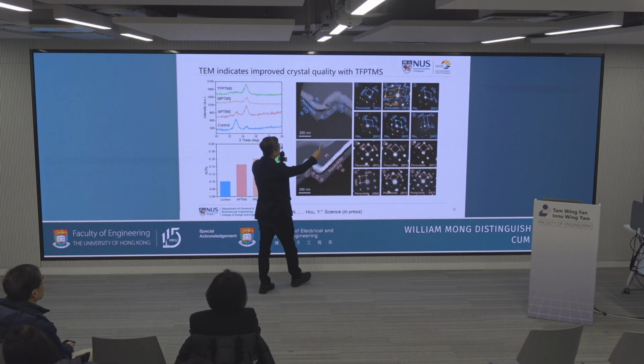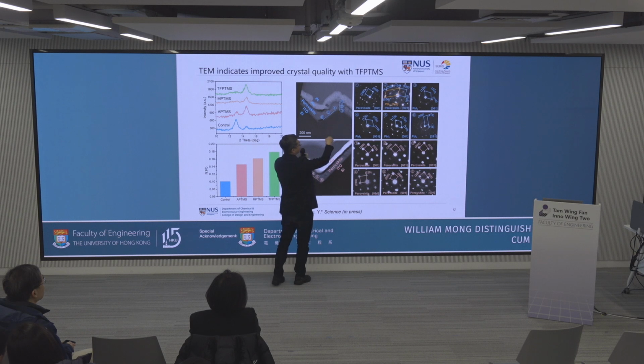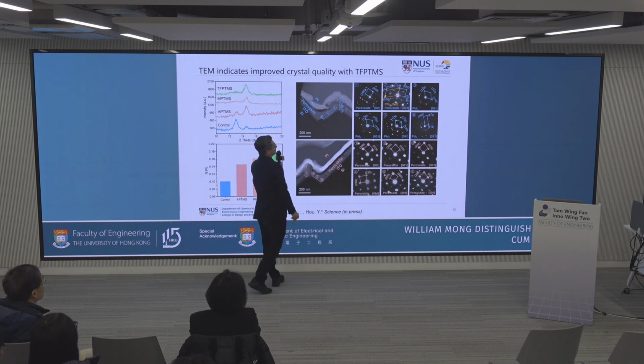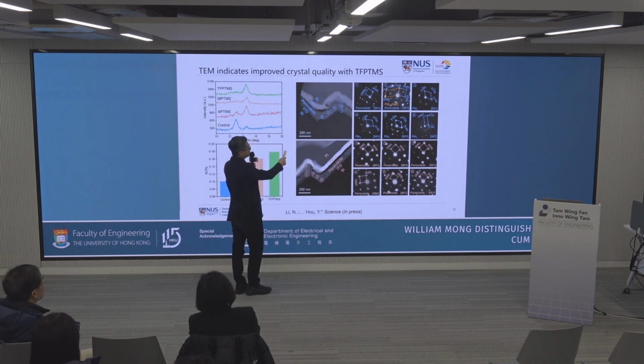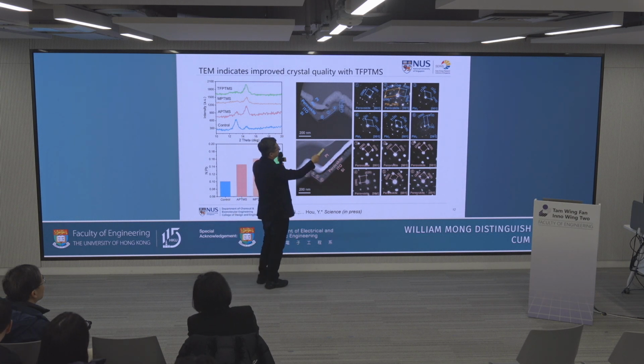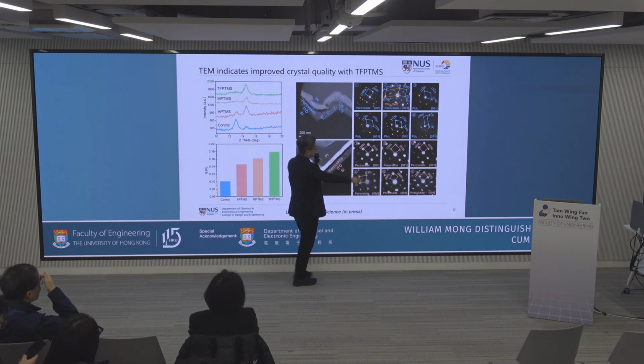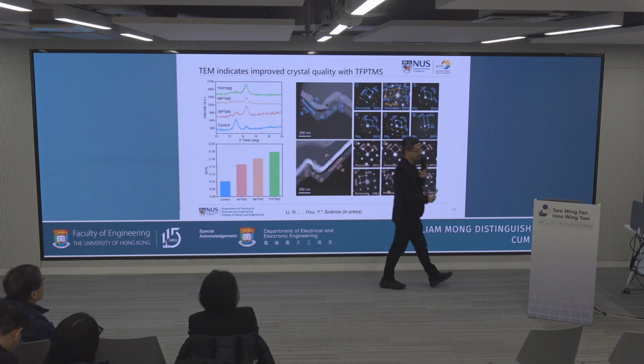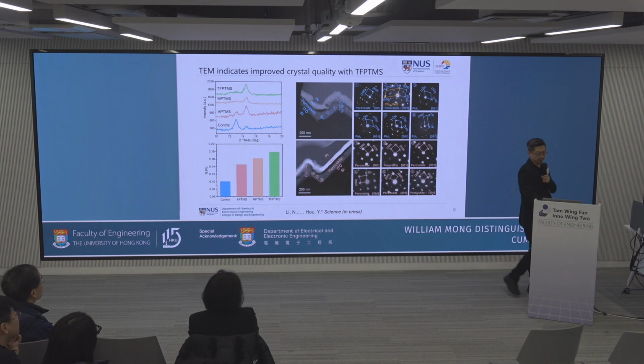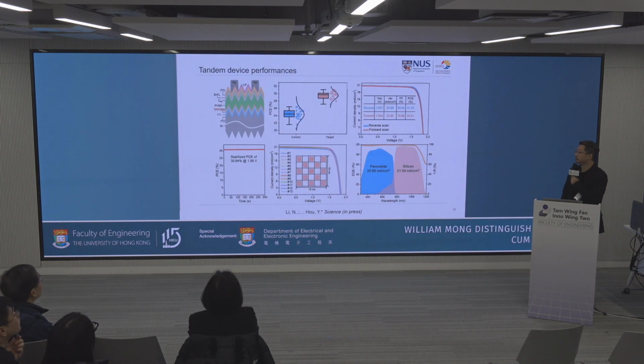And we check different spots, from the horizontal Z direction 1, 2, 3, and also these interfaces 4, 5, 6, each spot. And without this modification, you can see we can have a lot of just inorganic lead iodide formation. But with treatment here, you can see we can get a very high quality perovskite at different positions. So it's very homogeneous. So this is the evaporated perovskite on this industrial silicon.